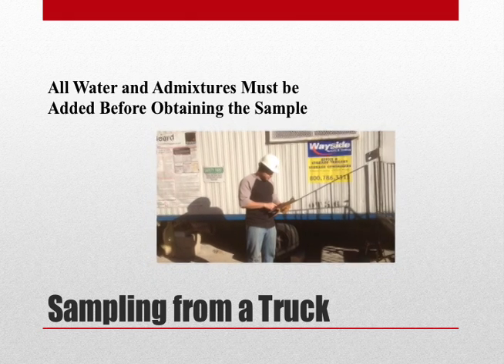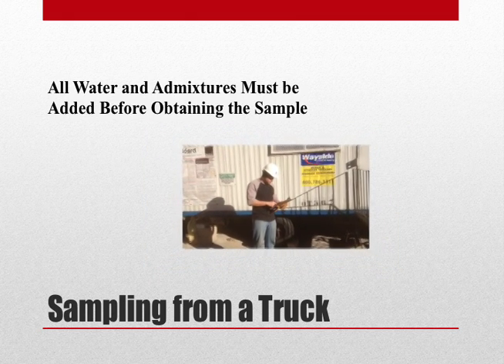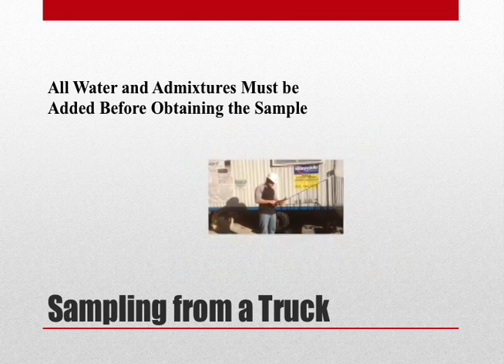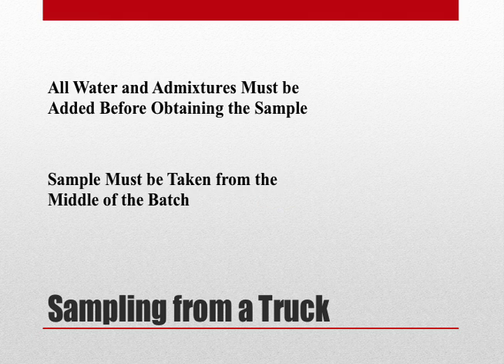When sampling from a truck, you want to ensure that all of the water and admixtures have been added before obtaining your sample. Furthermore, you want to take your sample from the middle of the batch and never the beginning or very end of the batch.